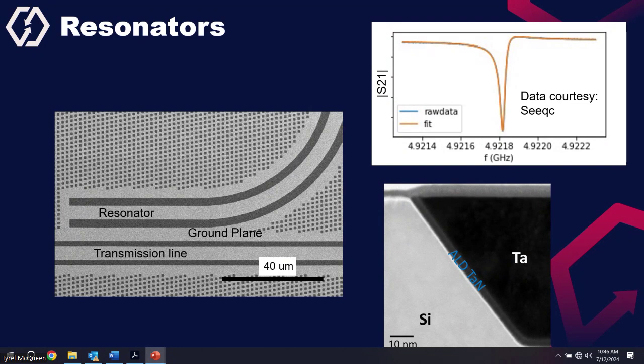So after the bottom electrode CMP is done, the resonator fabrication is done. So this is an example of an inductively coupled resonator. And the right-hand side shows the microwave transmission results for this resonator. So we got good quality factor from this, and we are still working on it to improve our quality factors in partnership with national labs and Seeqc. This data is taken at Seeqc, and the bottom image shows the TEM cross section of the side wall.